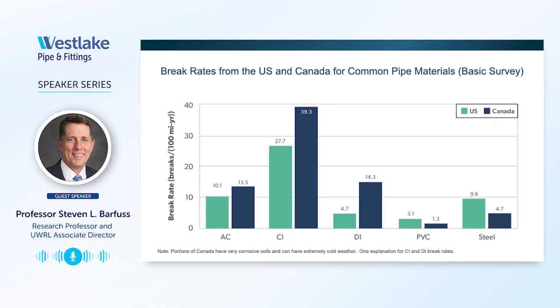Now, this is an interesting graphic because it shows Canada and the US in terms of these common pipe materials and their break rates. And you'll see immediately cast iron and ductile iron reported a much higher break rate in Canada than they did in the US. And again, we don't know the why of this perfectly, but we're supposing that some of it might have to do with Canada has some very highly corrosive soils. You're going to hear a little more about that from a Canadian here in just a minute. But it could be that, or it could be just the extreme temperatures. We're not sure, but as reported, that's an interesting data point.